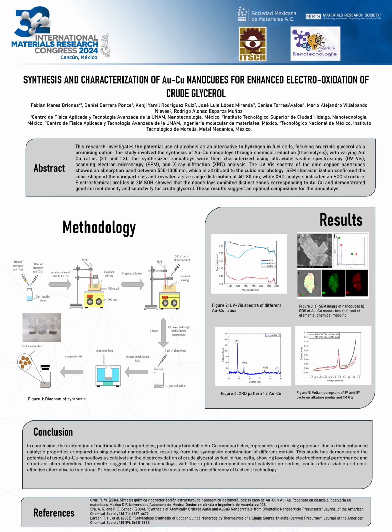And finally, the electrochemical profiles conducted in potassium hydroxide at a concentration of 2 molar showed that the nanoalloys exhibited zones corresponding to gold-copper. The nanoalloys demonstrated a good current density and selectivity for crude glycerol. These results indicate an optimal composition for the nanoalloys. The synthesis of nanocubes was carried out using the following methodology.